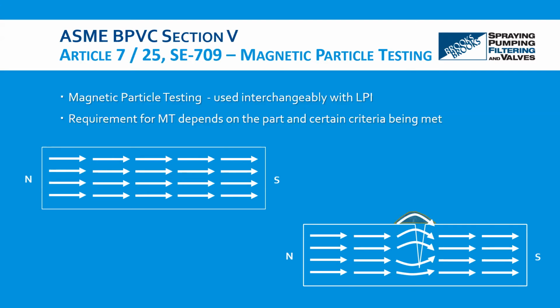And you can see here in the figures below a magnetic field being run through a material. In the top one, the field lines are nice and straight. However, once we have a defect, as you can see in the bottom figure, the magnetic field is altered. By then adding magnetic powder or particles, they adhere to that surface, giving a quick visual check to verify discontinuities.